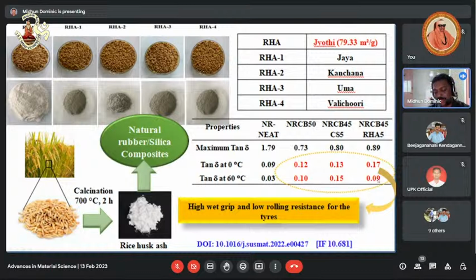So we could provide a new formulation for the development of green tires by the synchronized use of carbon black and rice husk ash. But even though the rolling resistance is decreased, we got a detrimental effect on mechanical properties like tensile strength, tear strength, and abrasion resistance. This is because rice husk ash has a low surface area, around 79, whereas commercial silica has a higher surface area, around 200 to 300 meters square per gram.